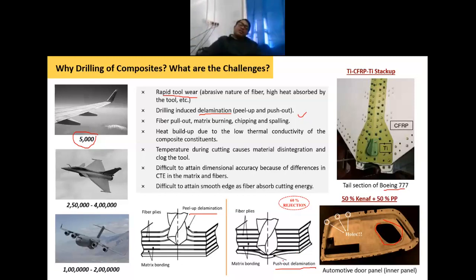And this push out delamination is more dangerous as compared to the peel up delamination. It causes 60% rejection in the aircraft industry. So if you make 100 holes, 60 holes will get rejected because of this push out delamination. So you can understand, it is a big challenge from the manufacturing point of view. So we need to find an alternative solution to address this issue.